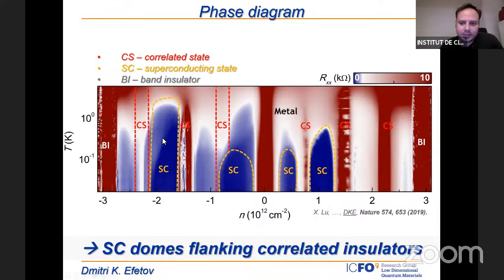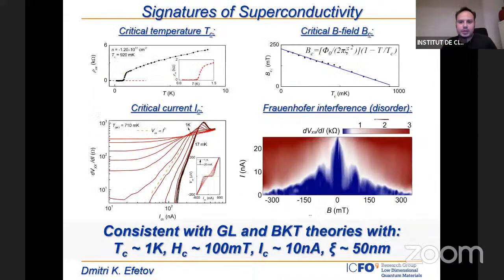In such a phase diagram, the red regions are resistive regions. Again, this is a color plot versus temperature. The red regions are where we still observe the correlated insulators, but flanked in between the insulators, we observed many superconductors. To convince you, we usually verify these superconductors by measuring R versus T and observing zero resistance. We also measure critical current: we measure dV/dI as a function of the bias current, and we observe a critical current transition, which is consistent with the Berezinskii-Kosterlitz-Thouless transition. I think the best proof right now for superconductivity is that, because of disorder in the devices, we also observe Fraunhofer interference patterns. So we really observe Josephson junctions in that system.